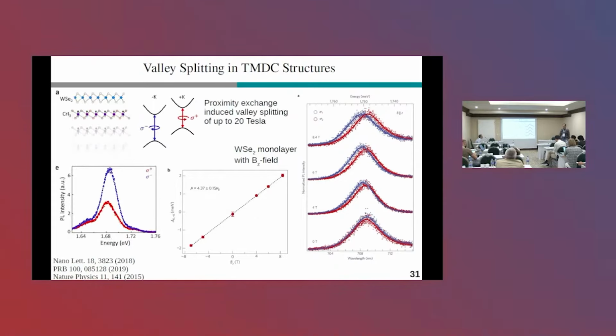So if you consider a tungsten diselenide on top of chromium triiodide, which is also a ferromagnetic semiconductor, then due to proximity-induced exchange coupling, a valley splitting of around 20 Tesla will intrinsically arise. So these are the data, and this additional quenching of one photoluminescence peak for the sigma plus comes from the band structure simply, but still these 2 peaks are split. That would correspond to around 20 Tesla of external magnetic field.